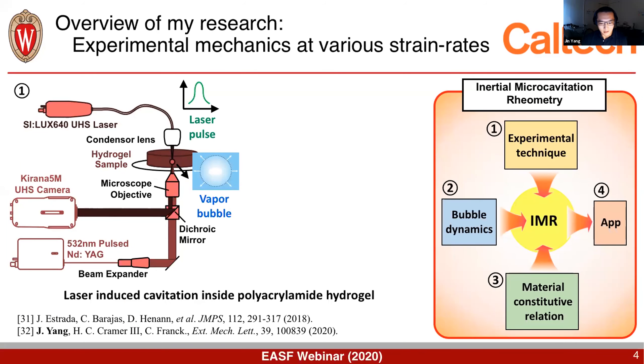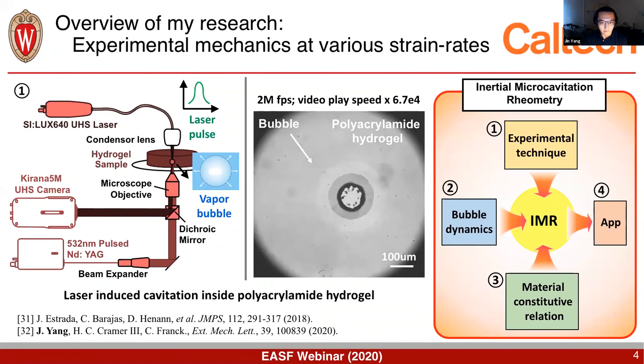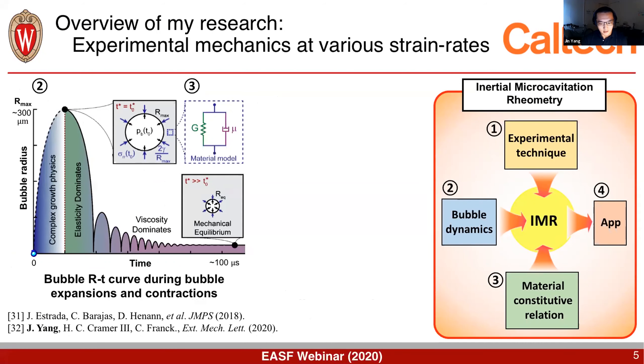In our experiments, we use a laser to trigger cavitation inside a gel. We also use a high-speed camera to take video of the bubble dynamics, and then use image post-processing to fit the bubble radius versus time curve. We study the bubble dynamics inside the gel, and by comparing the theoretical analysis of the bubble dynamics with the experimental measurements for the bubble radius versus time curve, we can extract the surrounding viscoelastic material properties.